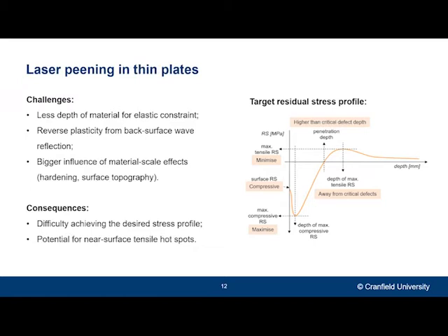project. If you look at the figure on your right, you can see what I would like the residual stress fields to look like. The objective is to get compressive stresses about 0.5 millimeter deep into the surface, so the compressive stresses can cover any lack of penetration defects. The magnitudes of that compressive stress should be as high as possible. However, it's also important to try to minimize the balancing tensile stresses that will also be formed, or at least